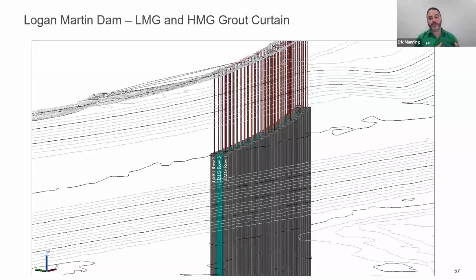It had been treated with the original grout curtain, but as I established, we've seen very little evidence that that original grout curtain is acting as a seepage barrier. I've cored a lot of holes out there, and I personally haven't recovered any of the original grout curtain. Although in other sections we have recovered traces of the original grout curtain, but I personally haven't in all the holes that I've drilled. But going back to this program, the goal is to establish containment in the more well-developed karstic features with the low mobility grout and come in between those two rows with our HMG grout curtain.